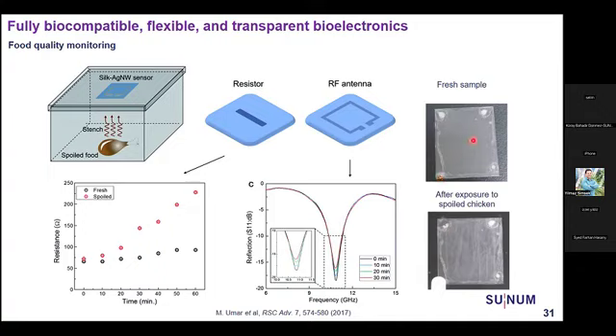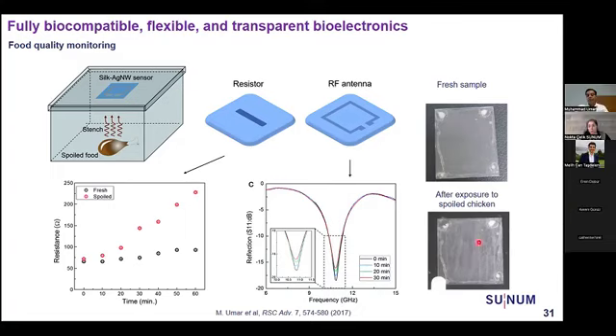So we made some simple tests on the glass. There are silver nanowires coated on the glass. This is the fresh sample. If we expose it to the spoiled chicken, we can see the surface has changed because of the corrosion due to the hydrogen sulfide gases.